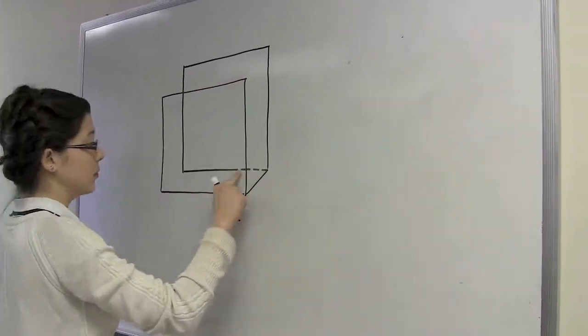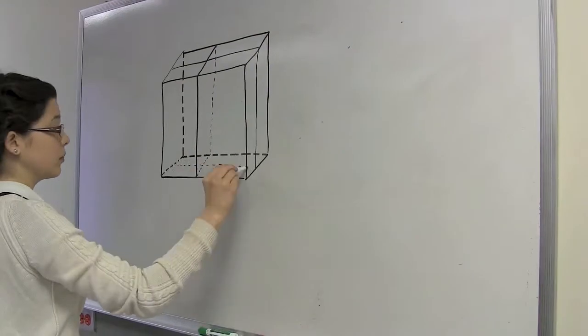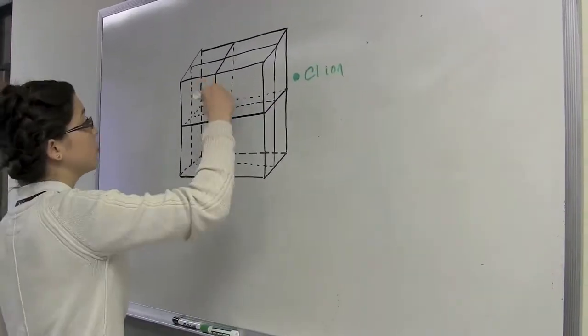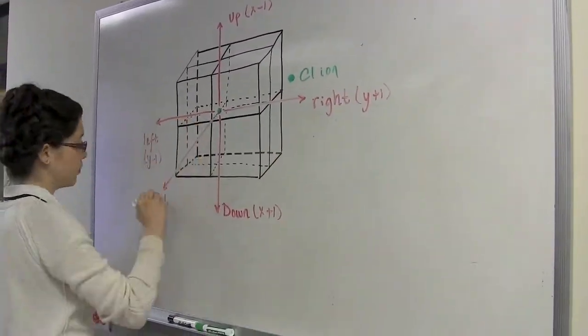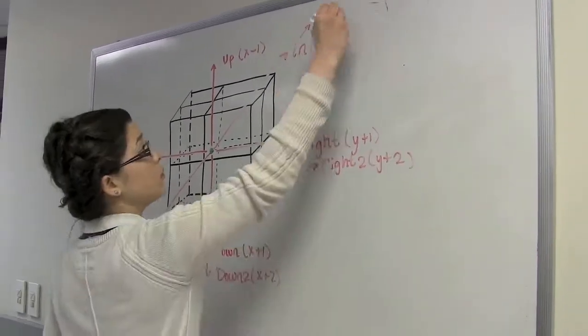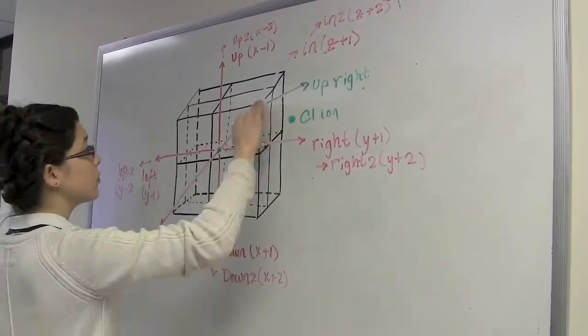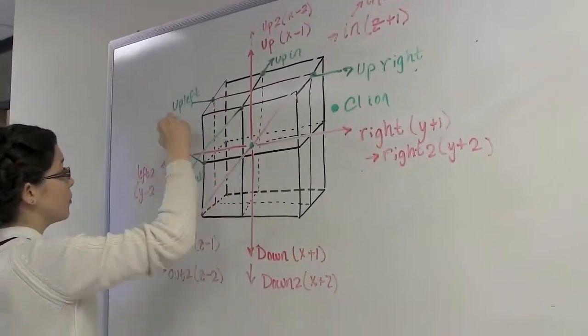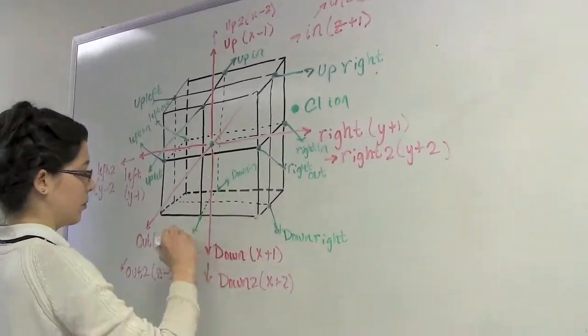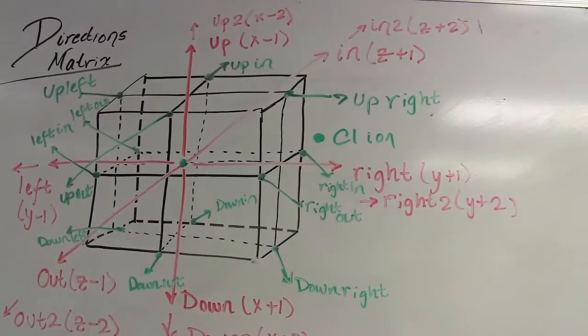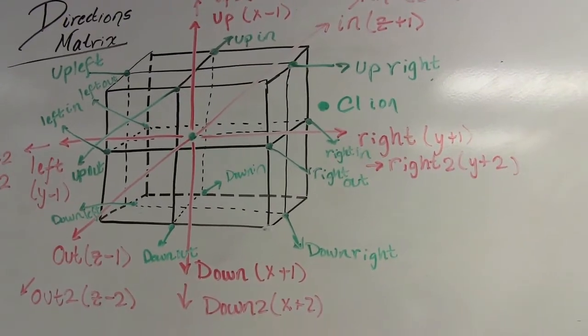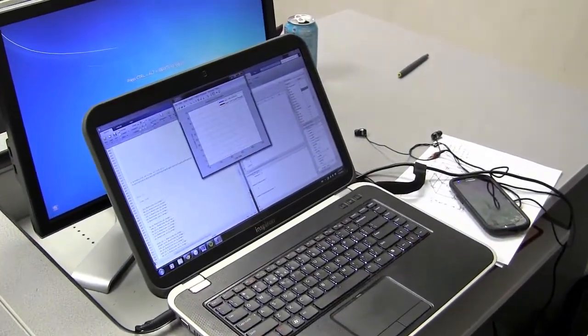When considering the ions inside the square lattice model dendrimer, the chlorine can hop in any direction where sites are available. The immediate sites in each direction and the secondary sites in the orthogonal directions were checked for openings and for dendrimer branches. This data is compiled to determine the relative hopping probabilities for each direction, and a new site was chosen for the ion. In a simulated bulk solution over thousands of time steps, the diffusion of chlorine ions into and through the solution was recorded.